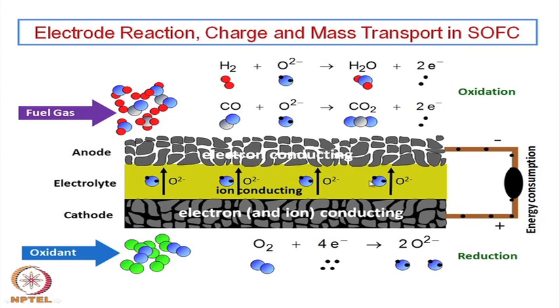So, this is one of the major requirements of this kind of system, the membrane electrode assembly. This compact layer can be called a membrane electrode assembly. Membrane basically because it has a semi-permeability only through oxygen, no hydrogen can go through, no other gas can pass through, only oxygen ion can pass through. So, it is basically acting as a membrane, although physically it is a very dense material. This oxygen permeability is because of the oxygen vacancy. So, it is the lattice oxygen that is going through, there are no physical pores in it.